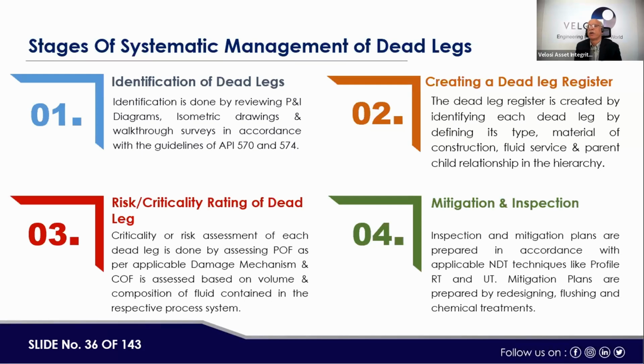Once you have a dead leg register, then we can do risk ranking or criticality rating assessment by identifying probability of failure and consequence of failure. And then once risk is identified, we can do the inspection planning also. Under probability of failure, we look at the applicable damage mechanisms and the growth rates, internal, external, or both. We also take care of consequence of failure, like effects on health, safety, or environment, and how much the inventory is, and so on.